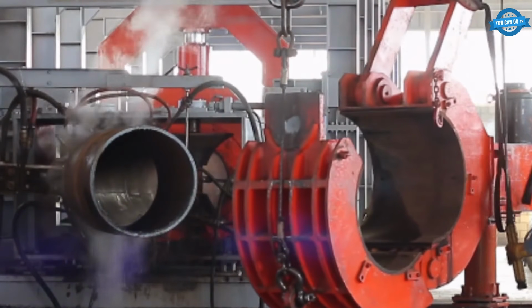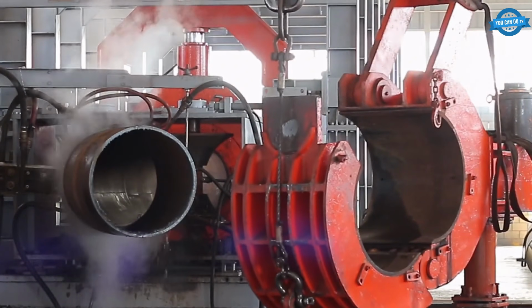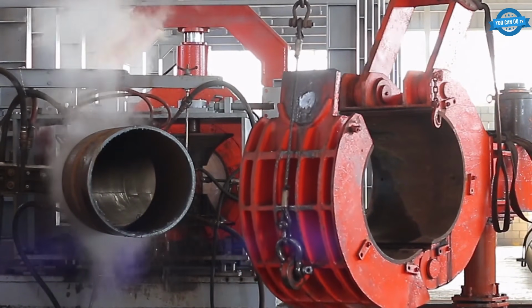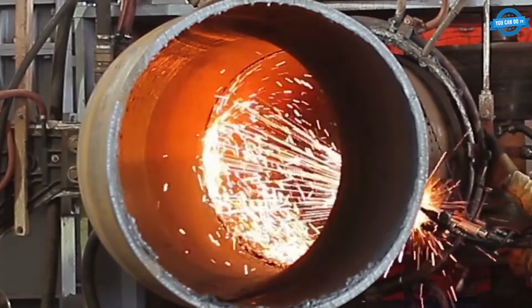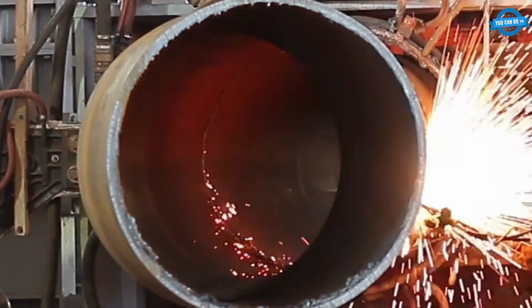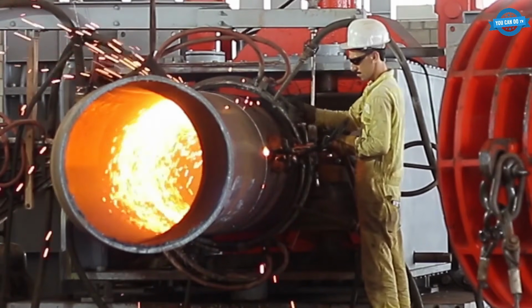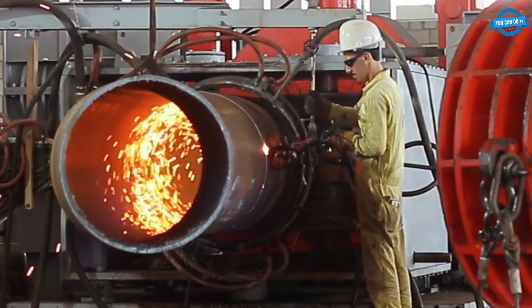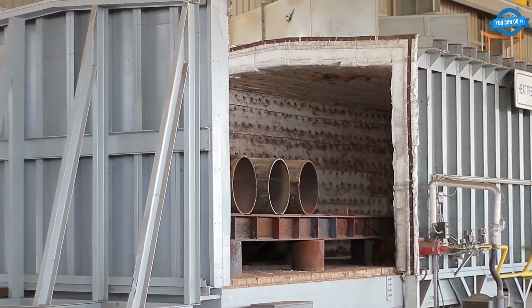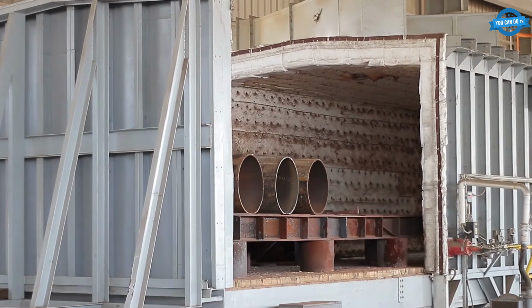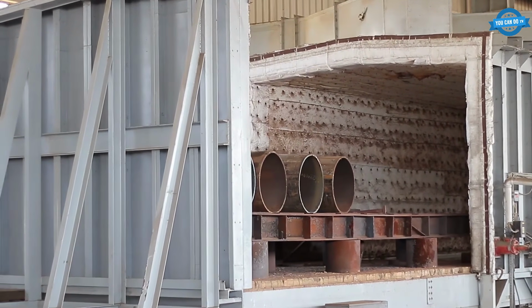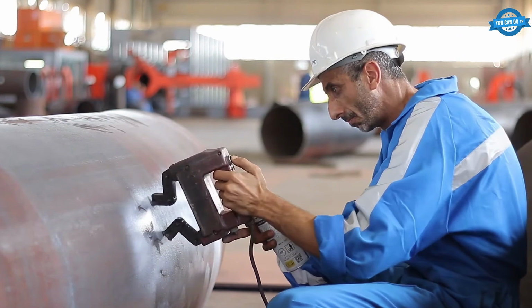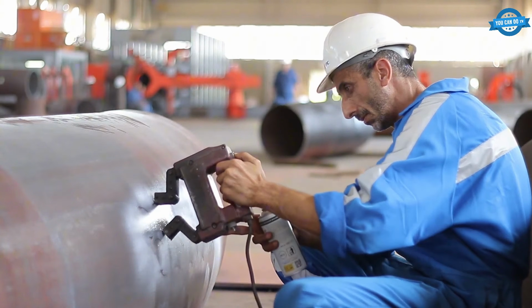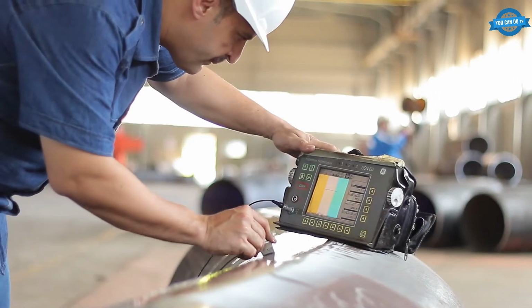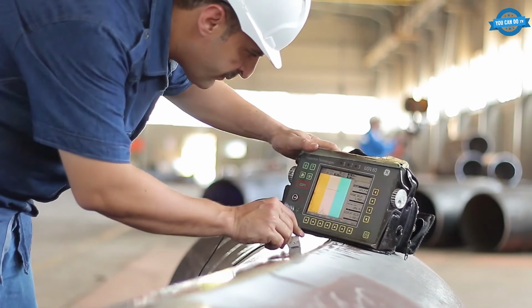Why is this hard? Bend a cold, thick wall pipe and it kinks, flattens, or cracks every time. Heat the wrong section and the pipe ovalizes beyond tolerance. The induction coil keeps the heat zone tight. Heat treatment then relieves residual stress. Destructive tests confirm mechanical integrity, magnetic and ultrasonic testing check flaws, and the ends bevel for field welding.